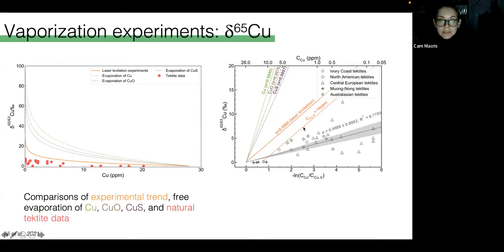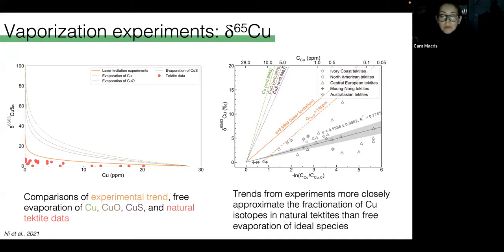Another line here is this dashed orange line. And what this represents is how that experimental line would shift its y-intercept if we plotted it using a different value as the starting concentration of copper. So in the dashed orange line, we use the concentration of copper that we find in those Muongnong tektites as the initial copper concentration, instead of the value that is estimated for the bulk silicate earth, which is what is used for this solid orange line here. But either way we plot it, the experimental trend comes closer to the actual tektite data than these curves for simple Rayleigh evaporation of ideal species. But we still see an offset between the experiments and the natural samples.